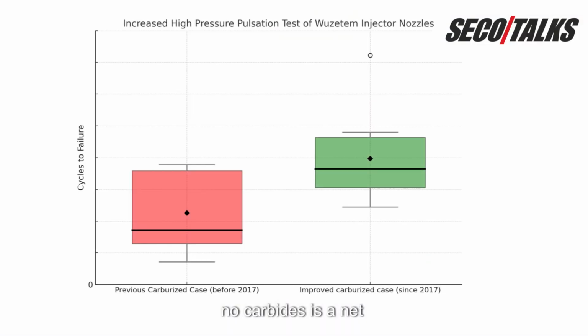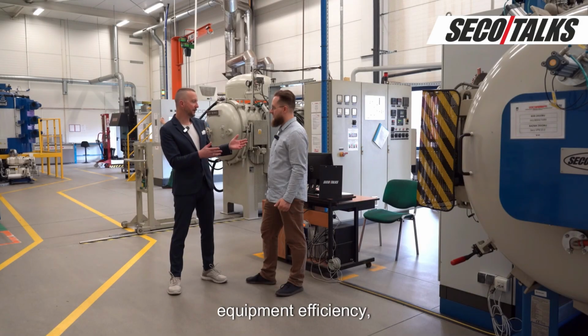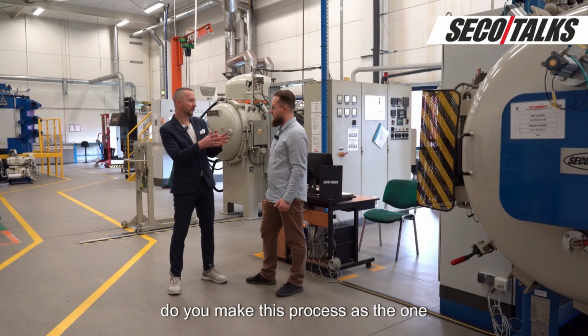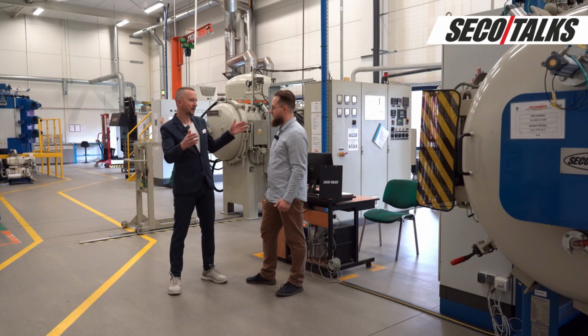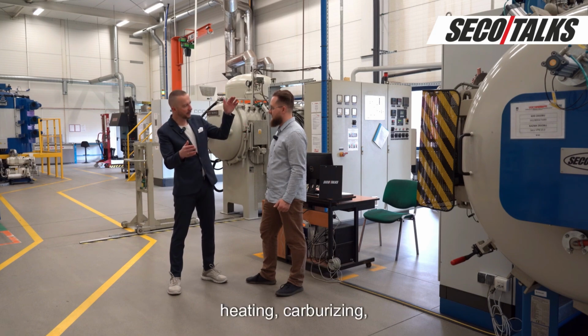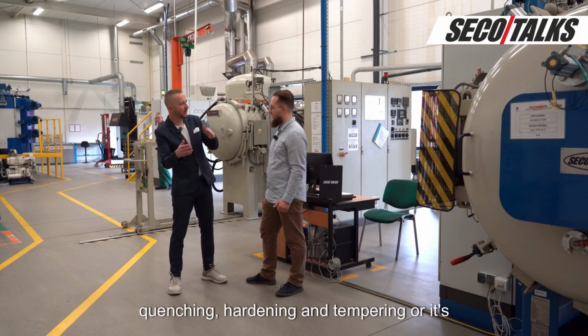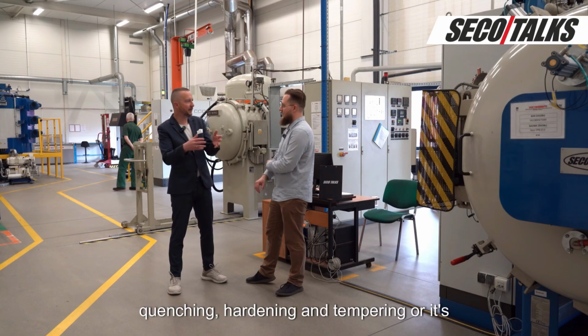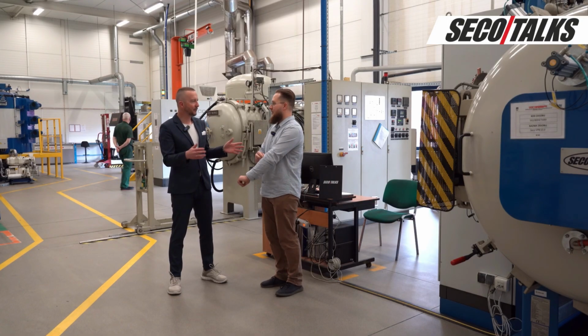So no carbides at all in the microstructure? No carbides in the carburized case at all. Good. And still the required hardness profile is maintained. From the perspective of equipment efficiency, do you make this process as one complete set of heating, carburizing, quenching, hardening, and tempering, or is it something in between?